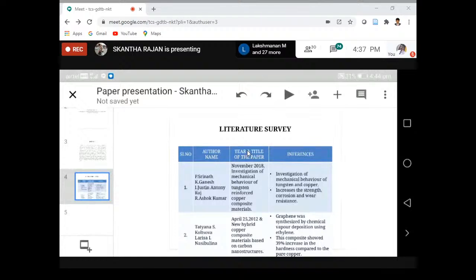Then the second literature survey is about graphene, a new hybrid copper composite material based on carbon nanostructure. They use copper with a carbon nanostructure. From the inference, what they say is that graphene was synthesized by chemical vapor deposition. Here they use the chemical vapor deposition technique to add the reinforcement. This composite will increase hardness by 39% when compared with pure copper.